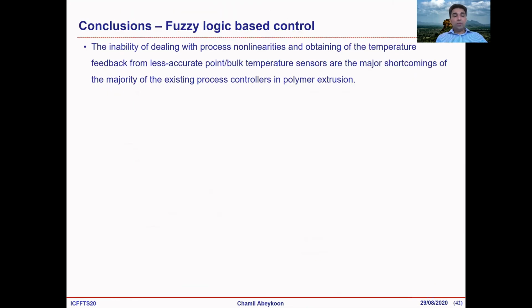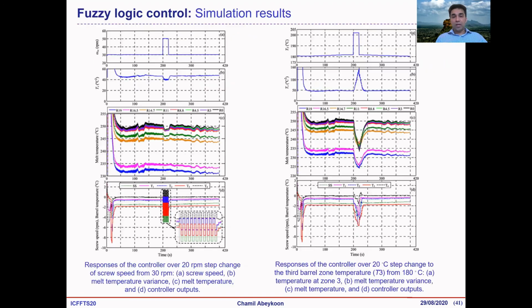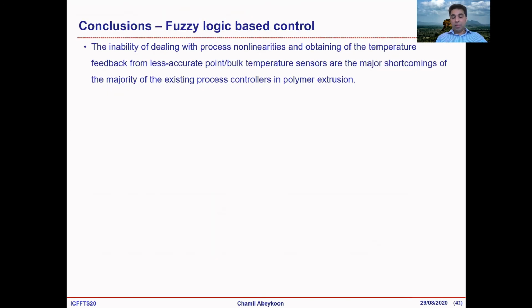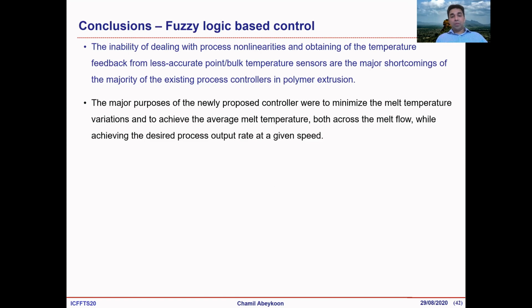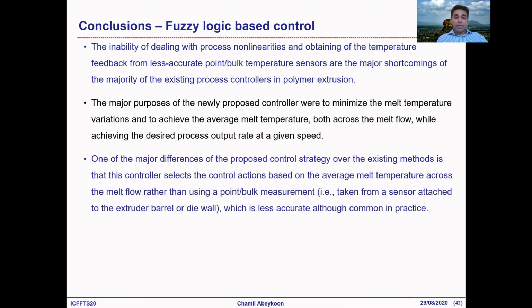Okay, so with that, we can recognize that as Fuzzylogic is being used for several other processes, we can introduce Fuzzylogic based control for the polymer extrusion process as well. So this is really recommended. Using this new Fuzzylogic control, we can minimize the melt temperature variation across the melt flow. As I said, this temperature variation could be even 70 degrees, but some industrial processes measure only 5 degrees variation, while the actual variation is as big as 50 degrees. Therefore, the new control should be important. So Fuzzylogic or neural nets or AI techniques should be really useful in that aspect, right?